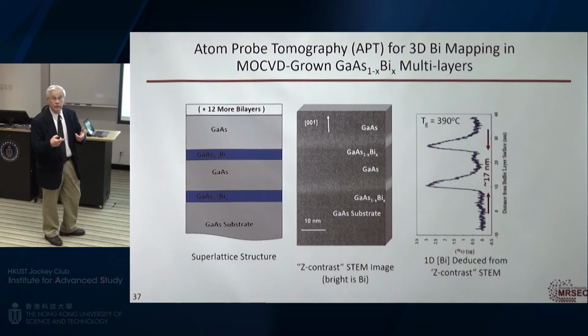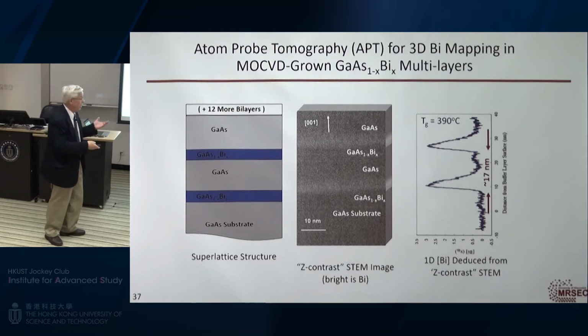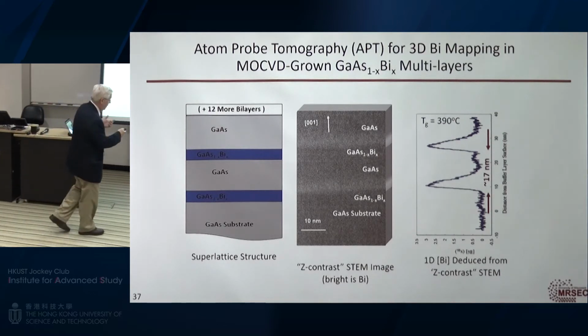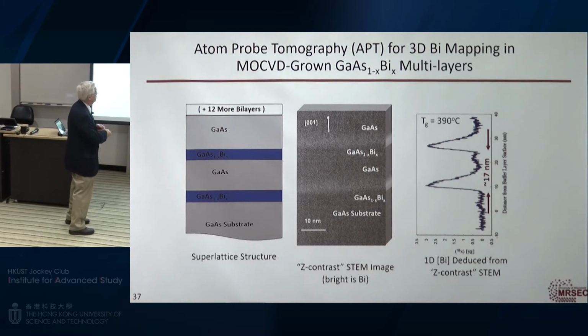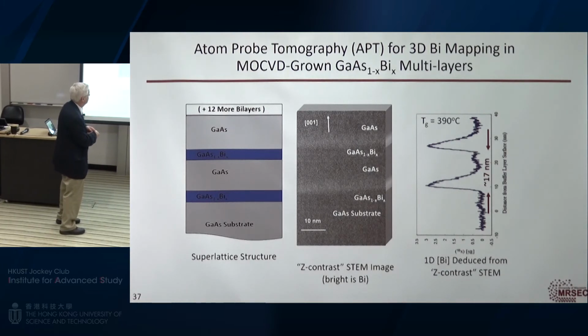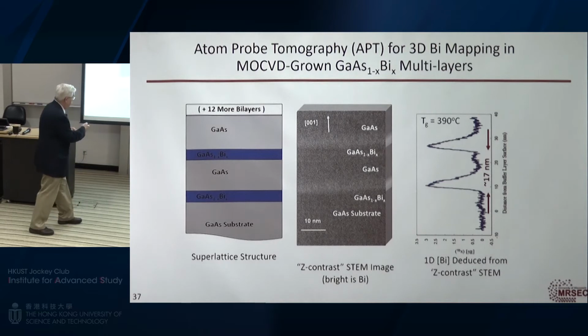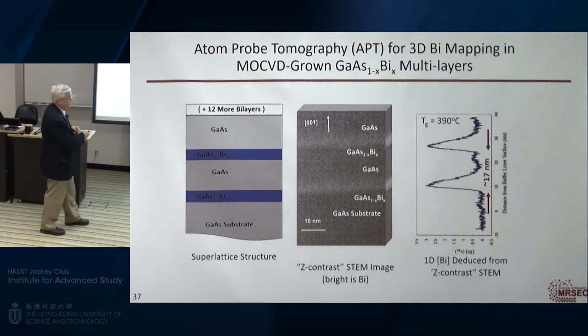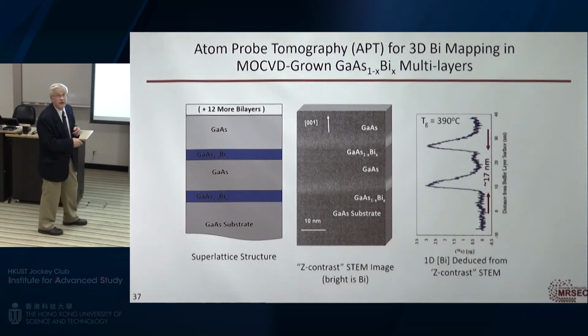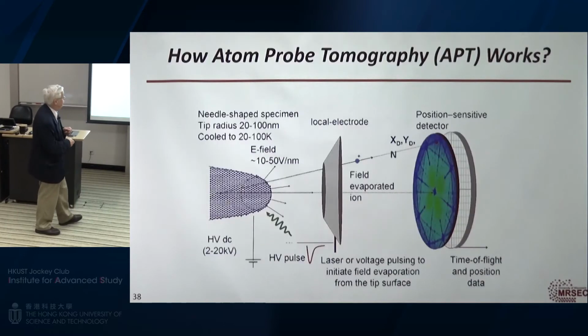So it's actually the reverse of what I'd expect. While I'm growing, there's bismuth riding on the surface, and when I stop putting bismuth in the system, that bismuth gets incorporated into the crystal. I should also point out that once it's in the crystal, it stays there, and we can make devices out of this once we get it homogeneous.